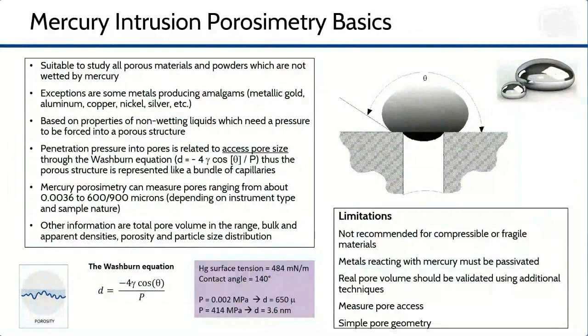The presence of smaller pores or compression collapse can be validated by comparing the skeletal and apparent densities or by measuring the BET surface area when applicable. Mercury does not wet most substances and will not penetrate pores by capillary action. Liquid mercury has a high surface tension, and molecular forces on the surface film tend to contract its volume into a form with the lowest surface area. Consequently, entry of mercury into pores requires applying a pressure that is inversely proportional to the opening size. The higher the applied pressure, the smaller the pores to be penetrated. The intrusion pressure of mercury into pores is related to the pore size through the Washburn equation. Knowing the mercury surface tension and the contact angle between mercury and the sample, the pore size range depends only on the applied pressure. Usually the lower applicable pressure is about 0.002 MPa and the maximum pressure 414 MPa, giving a measurable pore size range between 600–900 microns and 3.6 nanometers.